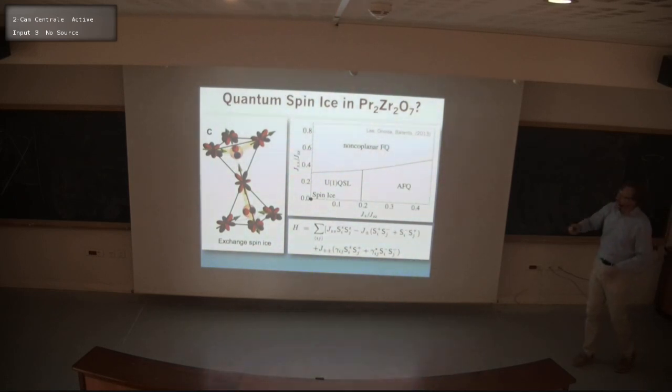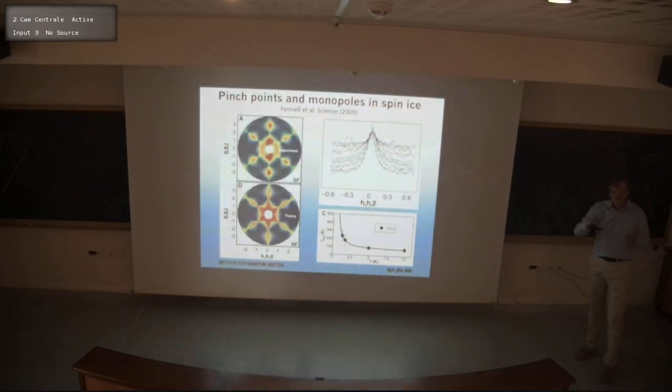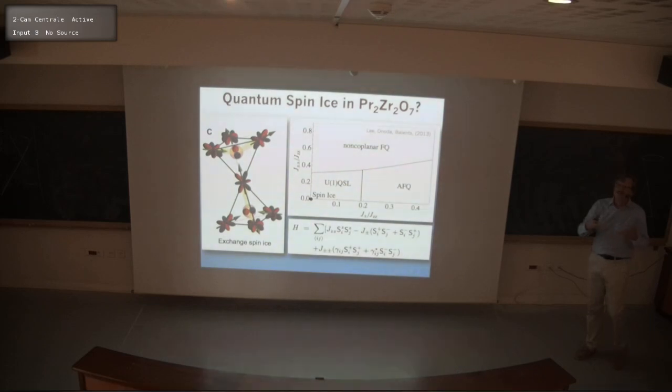In this case, on the other hand, because of the nature of the crystal field ground state doublet, we actually do have a Hamiltonian that will give rise to quantum fluctuations. And that has a very strong impact on the scattering experiments, because if you think about looking at a system like dysprosium titanate at low temperatures, I shouldn't actually expect to have any inelastic scattering at all. I should just have elastic scattering. So this beautiful image you saw here should specifically be elastic scattering. And so now we're interested in materials where we in fact do have quantum dynamics, and that will then mean that we'll have inelastic scattering in those systems at very low temperatures.